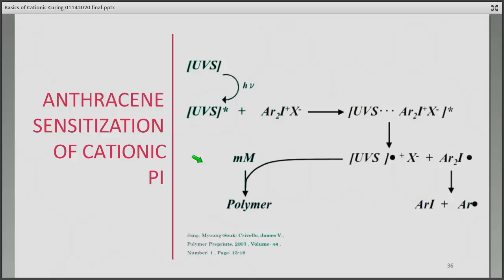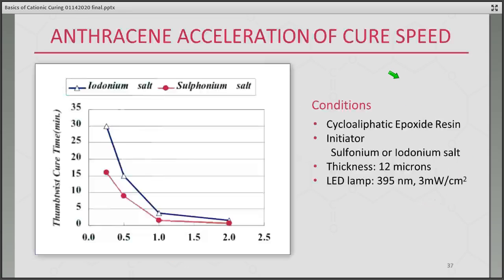Here's the mechanism. This is from work done by Crivello back in 2003. You have your sensitizer system exposed to UV light. It then reacts with a typical photoinitiator, here the iodonium salt, transfers the energy, and then allows that photoinitiator to do its thing and form the cationic system needed to kick off a photopolymerization.